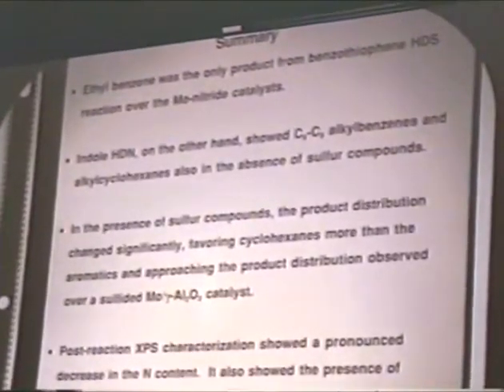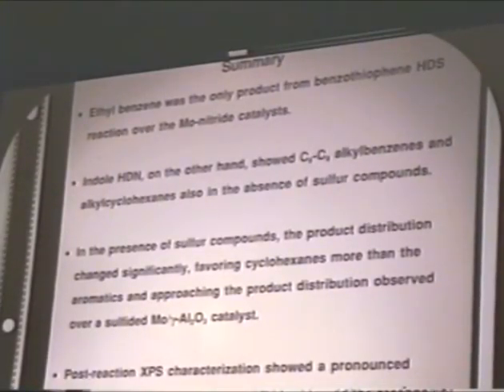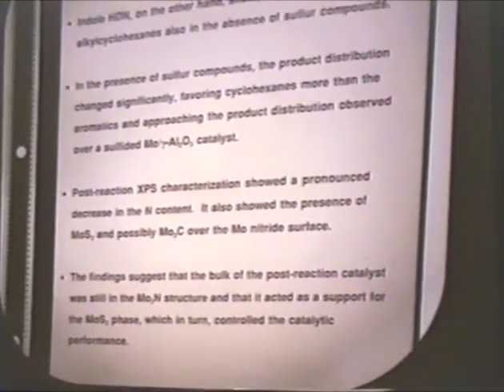Now, if we summarize what we have observed in this study, we saw that ethylbenzene was the only product from benzothiophene hydrodesulfurization reaction over the molybdenum nitride catalyst. Indole HDN, on the other hand, showed C6 to C8 alkyl benzenes as well as alkyl cyclohexanes in the absence of sulfur compounds. When we introduce sulfur compounds to the reaction medium, the product distribution changes very significantly, favoring saturated products, mostly cyclohexanes, more than the aromatics, and the product distribution begins to approach the one that is observed over a sulfided molybdenum catalyst supported on alumina.